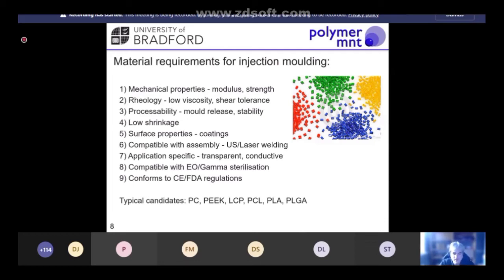We have to make sure as well that when our material has flowed into the mold, it's able to come out again. It's quite common sometimes with really, really small and sharp microneedle devices that you can have problems with material sticking in the tips of the microneedles that causes the microneedles to break as they're released from the mold. So this can be a real challenge. We want needles that have low shrinkage. So as they cool in the mold, they need to retain their shape, so we get that geometry that we require for use. And we may also want to consider things like surface properties in our molding to aid that mold release as well. So basically we can coat our molds with diamond-like carbon coatings or something like that, that allows us to release more easily.